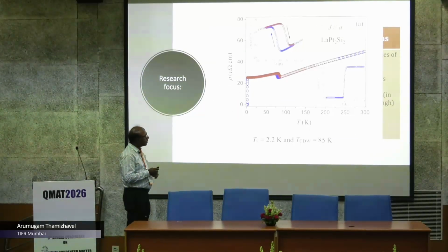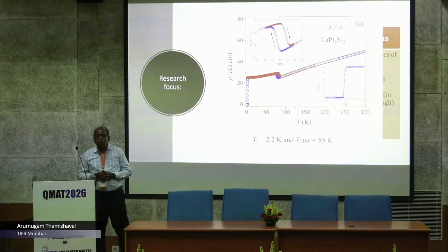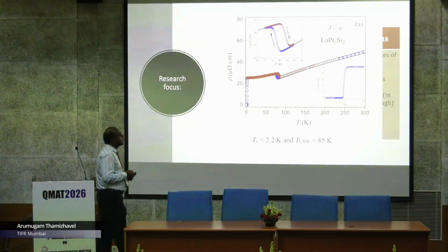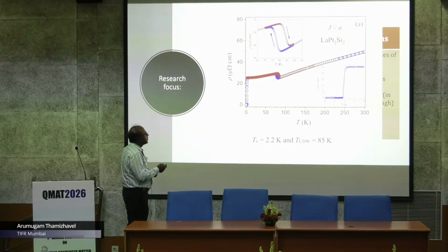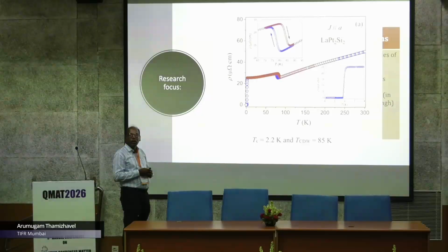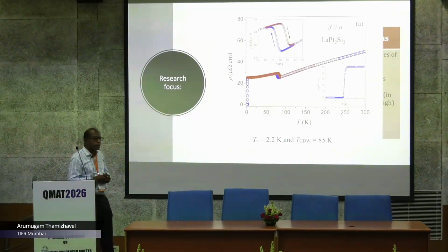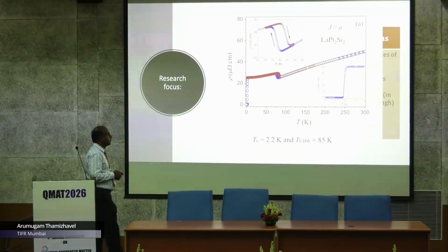We also work on charge density wave systems. For example, lanthanum platinum 2 silicon 2 is a charge density wave system. It exhibits a charge density wave at around 85 Kelvin, and also shows superconductivity. We have grown these single crystals and studied the anisotropic physical properties.